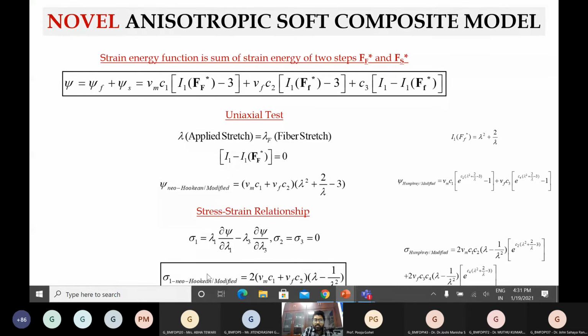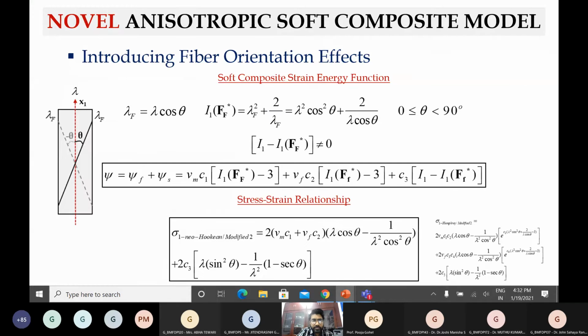What is the new thing which we have from before? We have a very simplified sigma versus lambda relationship, and we have C1 and C2. The new terms are VM and VF, where VM plus VF is equal to 1. They are the volume fractions, basically. So fiber volume fraction, how can we find out for a tissue? We'll have to take a piece of tissue and dissect it from the top and microscopically see at a certain layer what is the distribution of that. That's the only way of finding it. That information is fairly available, and we can throw that VF and VM value into this equation, and it boils down to that same curve fit equation. We also added a factor of fiber orientation effect. So what happens if the fiber is oriented at a theta degree or a certain degree from the actual direction of pull?